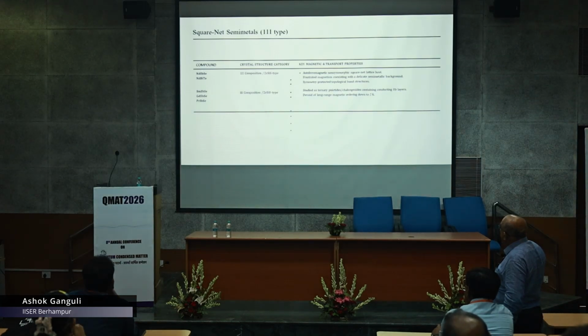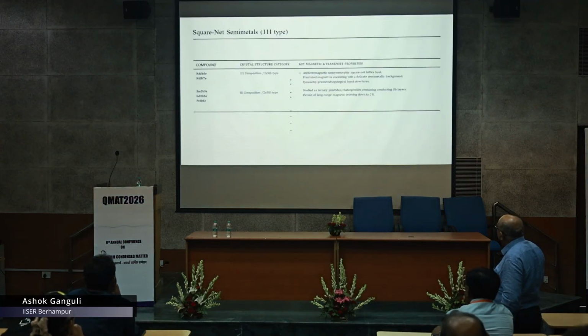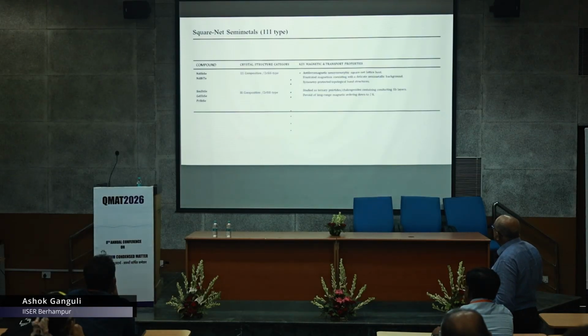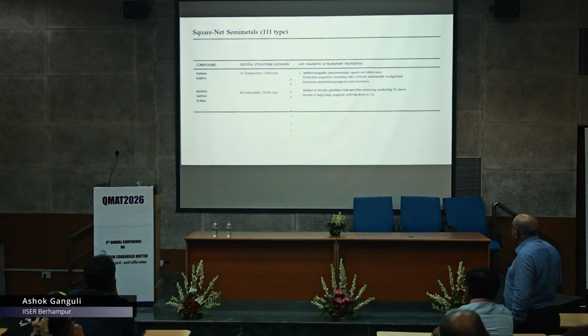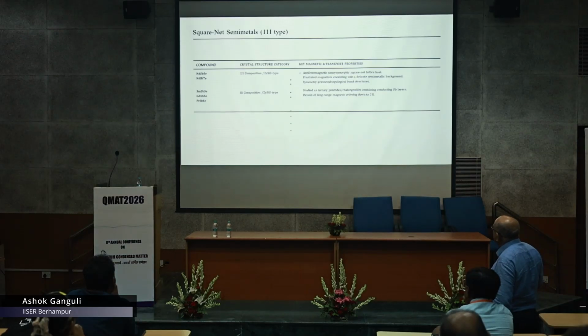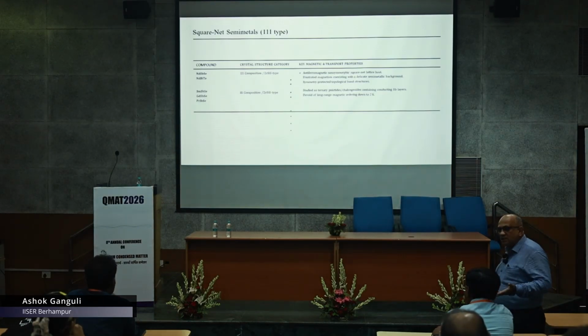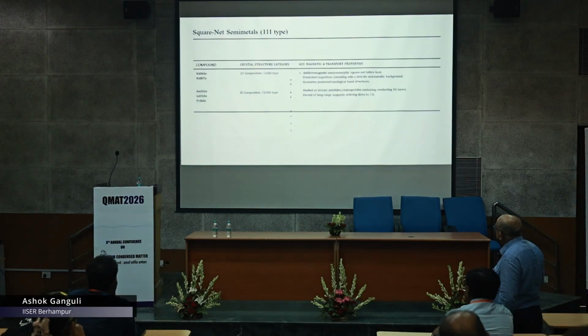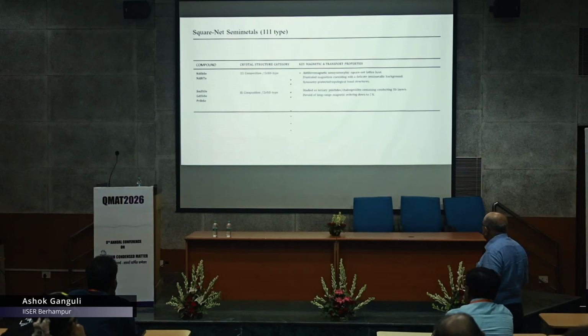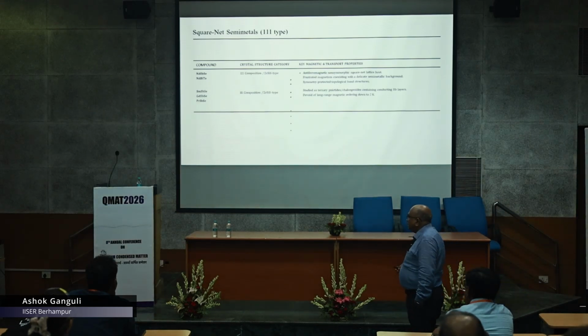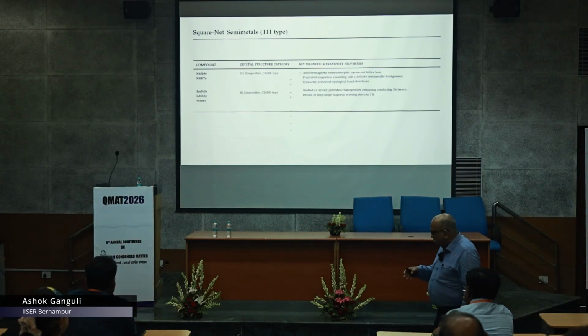NdSbSe is antiferromagnetic, a non-symmetric square net lattice, and shows frustrated magnetism coexisting with a semi-metallic background. NdBiTe has also got similar properties. It has a symmetry protected topological band structure. Some of them we have also done theoretical calculations. SmSbSe, again the same structure type, and many of these have short range magnetic ordering. Many of them have metamagnetism or spin reorientation, etc.